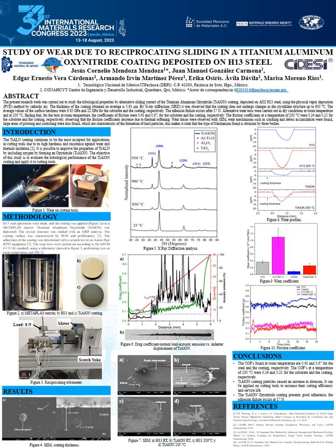Figure 8 shows the wear depths. H13 steel presents greater wear depths. The titanium aluminum oxynitride coating presents the lowest wear depth. This is due to its good mechanical and tribological properties, mainly its high hardness.